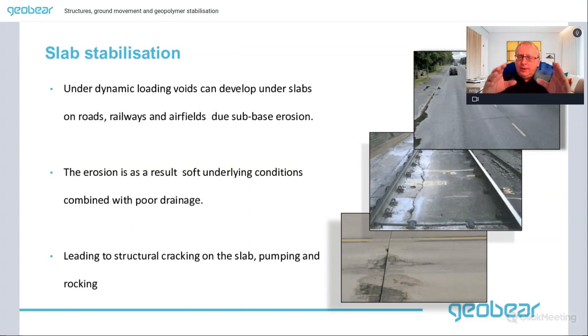So here we're looking at a road or a track bed, a concrete track bed, and under dynamic loading, voids can develop under slabs, and this can be on roads, railways, airfields, and this is due to subbase erosion. This is just a dynamic load from the vehicles or whatever machines are moving over the concrete pavement. You can develop voiding under the slabs. The erosion is as a result of either soft underlying conditions, or it might be combined with poor drainage. And this can lead to structural cracking of the slab and pumping, loss of fines and cracking. This is quite a common phenomenon.